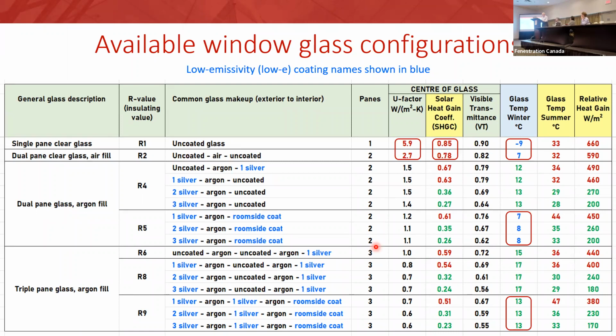So highlighting, we look now at glass surface temperature. This table tells us that our double glazed clear glass had a glass surface temperature of 7. Well, guess what? So does an R5 window, which has 2 low-E coatings, but one of them's on the room side. And that room side low-E coating is reflecting the thermal heat in the room back into the room. So the glass stays cold. The glass temperature is cold, but that low-E coating is still keeping the heat in.